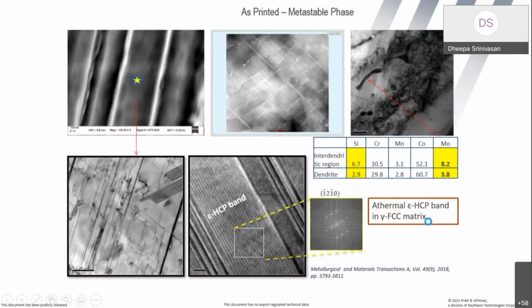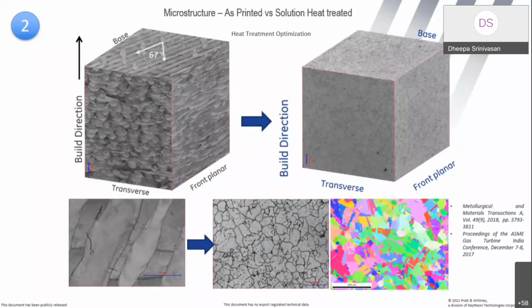So to summarize the microstructure in the as-printed condition, you see an athermal epsilon HCP band in a gamma FCC matrix. Of course, you have a whole bunch of precipitates out here. We have discerned the nature of this precipitate from this high angle annular dark field image, and I'll be sharing that with you shortly. So then we went on from the microstructure. We need to give the pre-weld and the post-weld heat treatment, because remember, we are going to weld this particular part to the cast FSX 414.